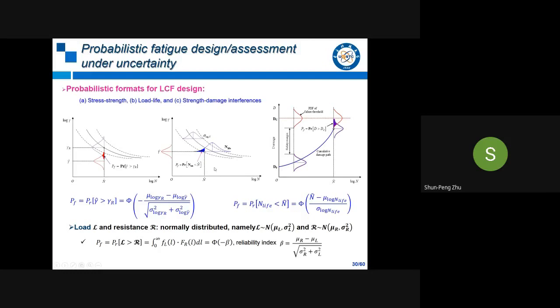And the second one is the load-life interference. For a given number of loading cycles, we can estimate its failure probability according to the life distribution of this stress level. The third one is the strength and damage interference. This is a damage point of view. Damage is accumulated, and for this accumulated damage, we can model the tendency and quantify the failure threshold and also the cumulative damage behavior, to find the failure probability or to design the life. So here are the three interference mechanisms for fatigue reliability design or analysis.